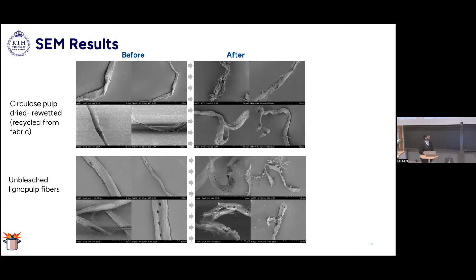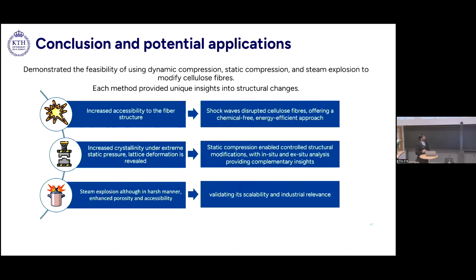So this sums up my entire thesis mind map. To conclude the entire argument, we have established how we can treat cellulose in three different ways: with shock waves, with static compression, and with steam explosion. Each method provides its own perspective on how cellulose structure can be changed. Particularly from shockwave treatment, we have increased accessibility of the surface area. After the shockwave treatment, the shock waves are disrupting the fiber structure completely.